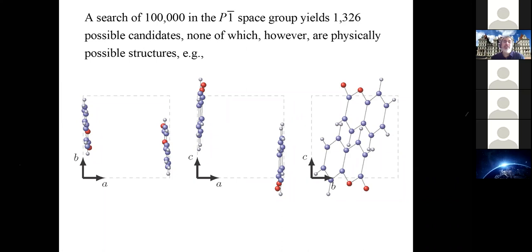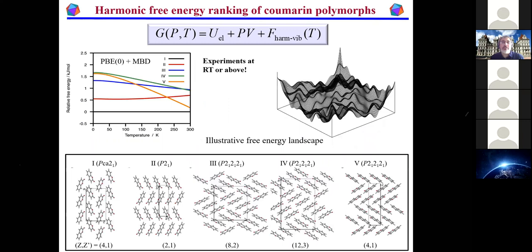So if you can't find any physically reasonable structures in a given space group, you check it out, right? And so that's sort of where we're going with this topological crystal structure prediction idea. And so far it's looking very, very promising. We've looked at molecules other than coumarin. We went back to the blind structure prediction molecule, and we found that we could get, again, this experimental structure using only topological considerations. But I want to move on to something else, which is, what about ranking polymorphs?